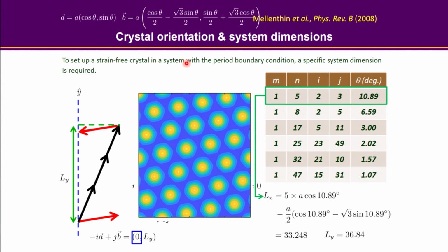Okay, so let me see if I have, yeah, I already timed. You have to use this 4 pi over square root of 3 because in your evolution equation, you have already set this Laplacian plus 1 kernel. So that 1 is already there. Because of that 1, for a triangular lattice, you really have to use A equal to 4 pi over square root of 3 in my calculation. Okay, but still I have a few things to say before we can close this part.